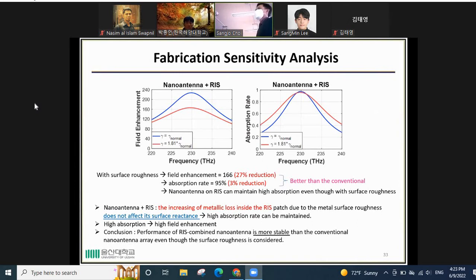And also, this is the good feature from our structure. We can maintain the 95% absorption rate, even though we consider the surface roughness. This is also better than the conventional nano antenna over the grounded substrate. So from this, we can say that for the nano antenna combined with the RIS, the increase of the metallic loss because of the surface roughness doesn't affect its surface reactance, so that high absorption can be maintained. So we can also conclude that performance of the RIS combined nano antenna is more stable than the conventional nano antenna array, even though the surface roughness is considered.